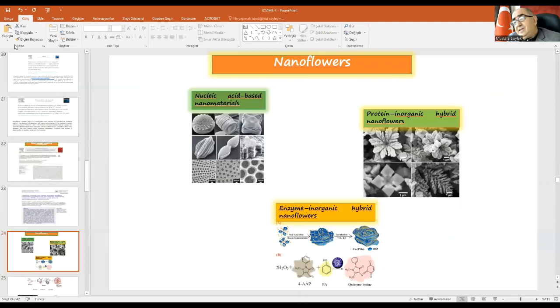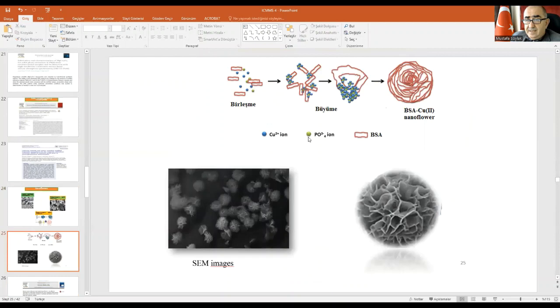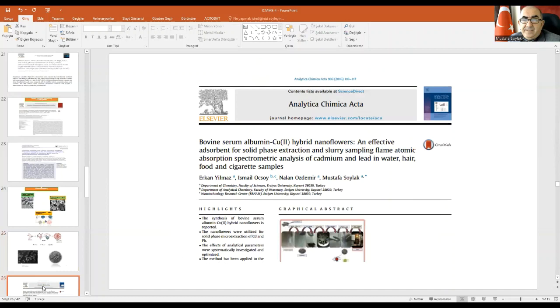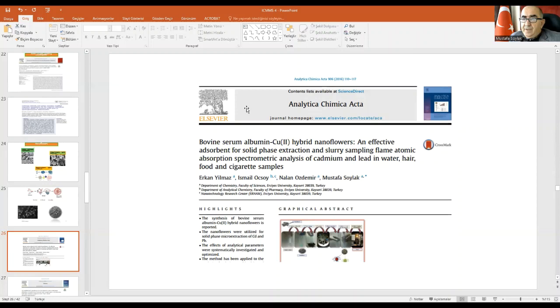Another attractive material we used for the solid phase extraction studies is nanoflowers. Here you can see some images of nanoflowers. There are different kinds of nanoflowers we can synthesize. Here is one of our nanoflowers. We prepared it from copper II and phosphate plus bovine serum albumin, and we used these materials for the solid phase extraction of cadmium and lead ions from different samples.